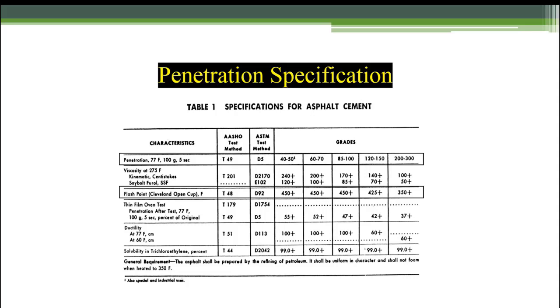So just a thing to remember, and we'll get at the reason for still retaining this pen graded idea: number one, a lot of our older pavements, when we look at them for RAP, were built with an asphalt specification that was pen graded, penetration graded. 85 to 100 was kind of a standard pen graded asphalt cement that was used long before the PG binder specification. The next thing I wanted to point out, and it's boxed in there, is flash point.